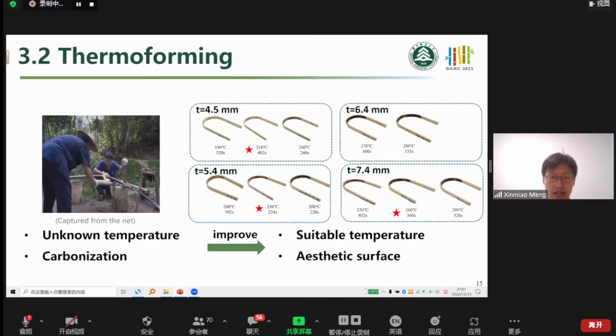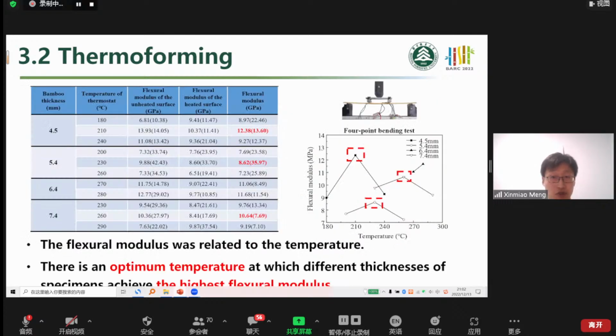Like Professor Zhuo mentioned, we can use thermoforming to make the curved bamboo, but the temperature is unknown, and the carbonization of the surface cannot be avoided. So we want to improve the thermoforming process and obtain the suitable temperature range. We studied different thicknesses of the bamboo strips and applied different temperatures. And we also conducted a 4-point bending test.